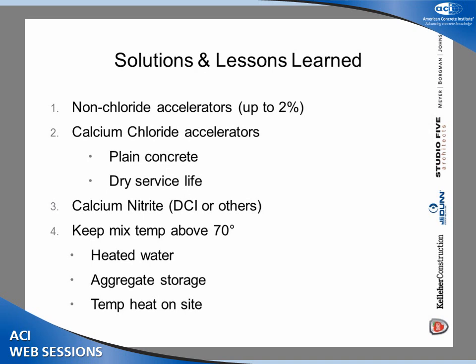Here's some of the other things that are critical, especially in cold climate, cold seasons: keep that mixed temperature above 70 degrees. That's critical. You do that by heating the water, which is also expensive, but it is very effective. Keeping the aggregate somewhat protected in a tempered space where it doesn't get snowed on and left to the 20 below temperatures. You introduce that ice cold aggregate into that mix, and it drags that temperature down dramatically. And of course, temporary heat on site during the day of the pour, the night before, is critical.